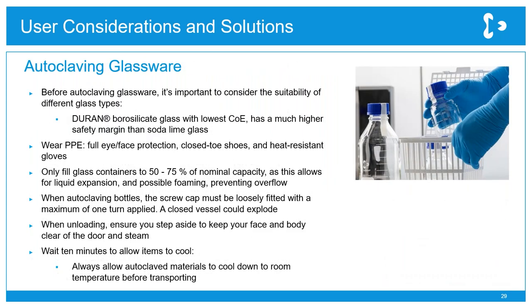And related to heating is autoclaving, which is extremely common in the lab. And we recommend that only borosilicate glass is autoclaved and not soda lime glass. When you're autoclaving, we should be wearing full PPE, and some liquids and media are prone to foaming, so don't fill the container more than 3/4 full. This will allow liquid expansion and prevent overflowing.